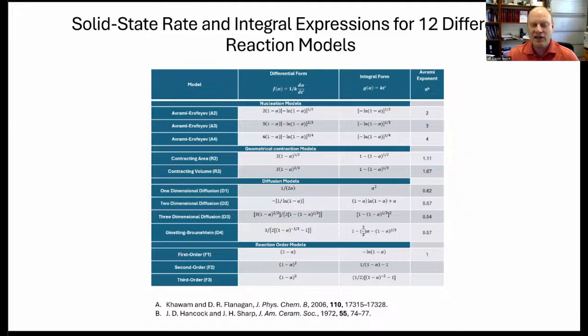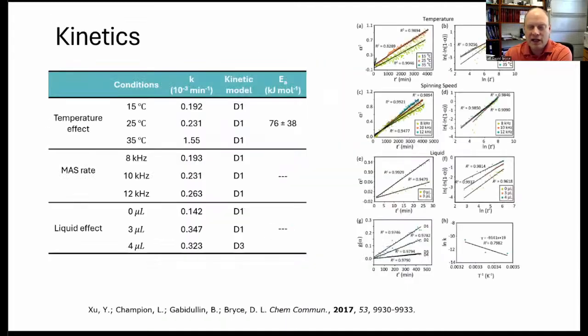And by analyzing these data using various possible solid state models, we can fit the data. And in this case, we get a diffusion controlled model, 1-dimensional diffusion in most cases. The best fit was 3-dimensional with more liquid added. There's a bunch of plots here I'm not going to walk through, but we analyzed all these data.